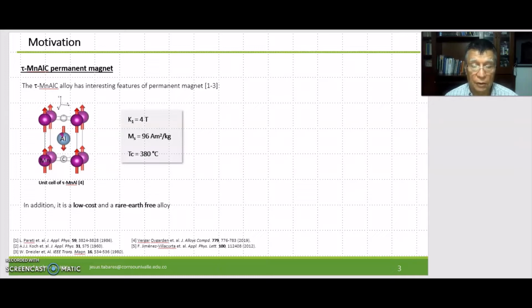A rare earth-free alloy to consider for permanent magnet applications is the face-centered tetragonal structure of the near equiatomic manganese aluminum alloy, stabilized by a very low concentration of carbon, between 1 and 2%. This alloy is called tau manganese aluminum carbon alloy. This alloy exhibits good permanent magnet properties, such as high anisotropy, a relatively high saturation magnetization, and a moderately high Curie temperature. Besides, it is a low-cost material.